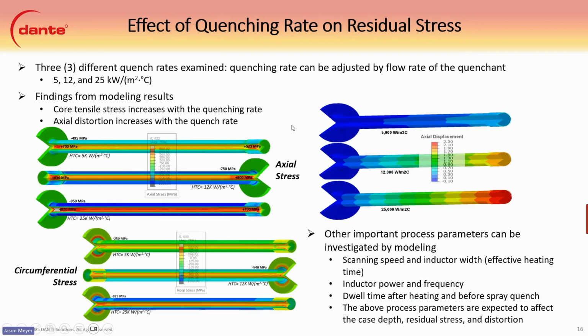So, the results showed us, you can see the middle section here that was done with the 12 kW/m2°C quenching boundary condition, where it shows pretty significant tensile stresses along the core of the shaft, with more near the flange end, and it shows a good compression at the surface of about 750 MPa. The reason we see the difference here in stress, and there's a big peak stress, is with induction hardening, the near surface is the region that's transformed. Compared to a furnace heating process where the whole body is heated, there needs to be a stress balance. And in induction hardening, if you only transform that smaller surface, you have to have a stress balance from that compression only in that near surface. So we usually see a very high tension underneath the induction process because of the stress balance there.